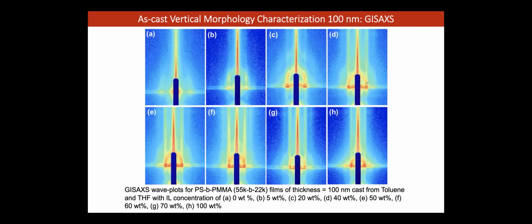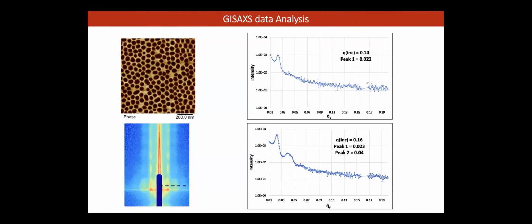And if we can actually pull out tortuosity and then confirm it with some three-dimensional microscopy technique like Hiroshi Jinnai does, with TEM beautifully as a function of depth, which is really laborious but amazing. If you can correlate tortuosity directly from GISAXS, that's the kind of thing that's needed for the field in the future. But this just shows you that this has both a vertical component and an isotropic component. And then this needs to be studied as a function of the critical angle.